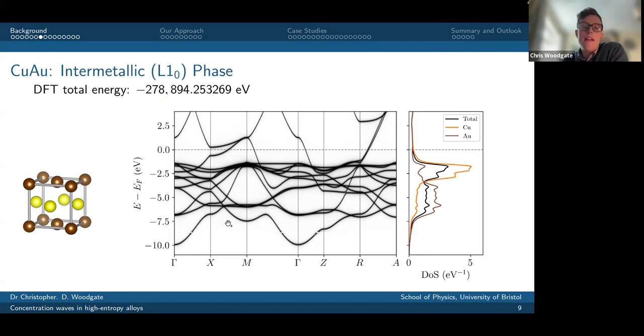I've actually plotted the Bloch spectral function here, so there's a small imaginary component to the energy, so the bands don't look quite pristine, but believe me, if you take the limit of zero energy, you have pristine, perfect band structure. And in principle, you have zero residual resistivity. If you cool the system down to 0 Kelvin, your Bloch states are eigenstates of the Hamiltonian, and my electronic mean free path is in a sense infinite.